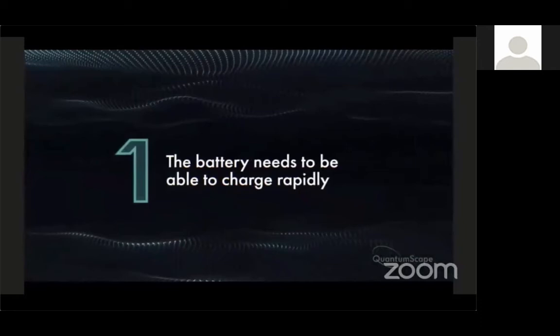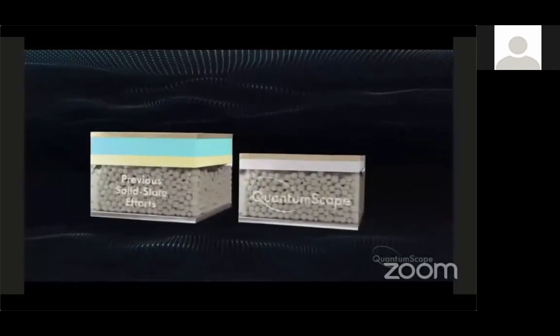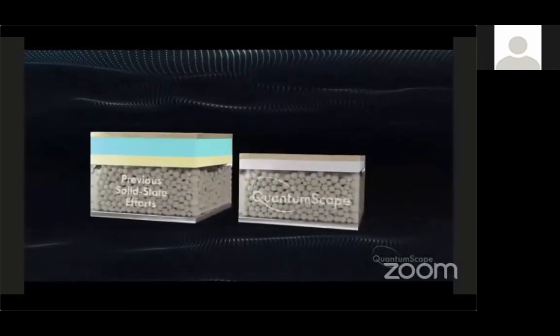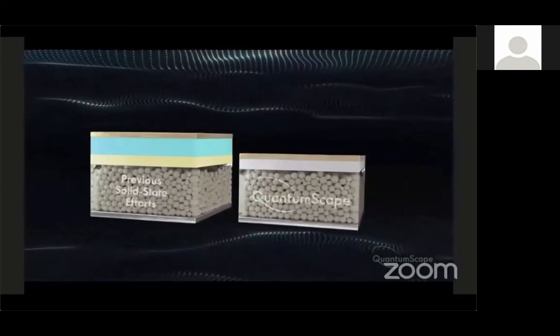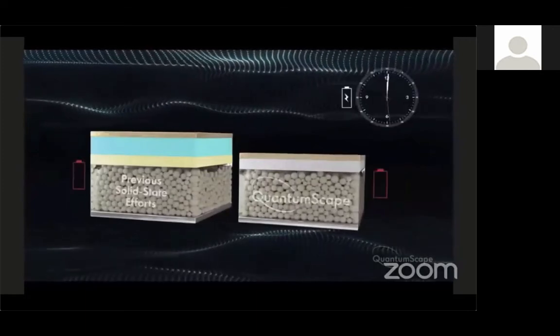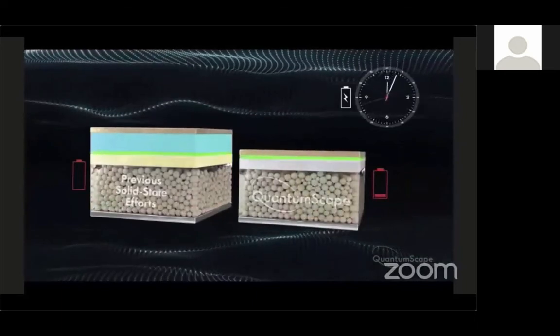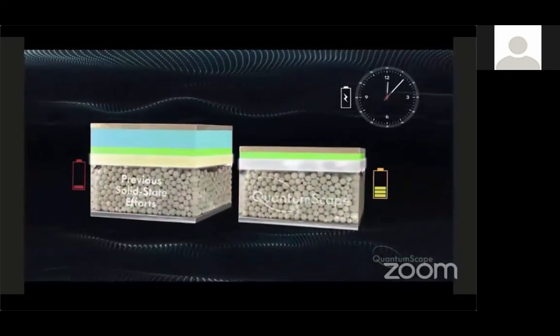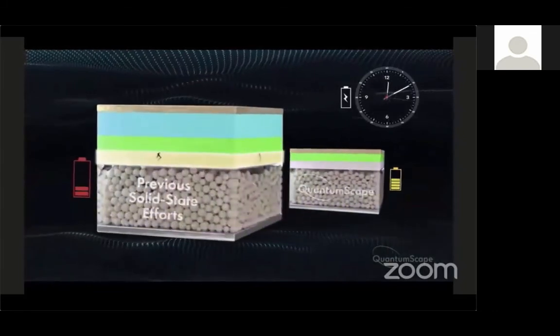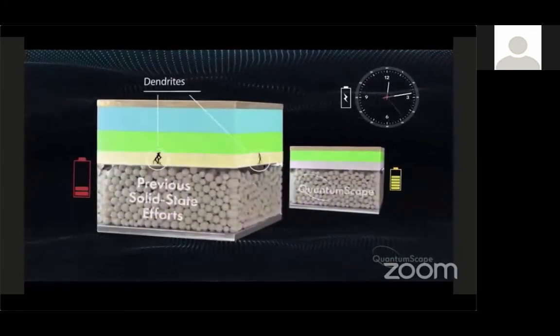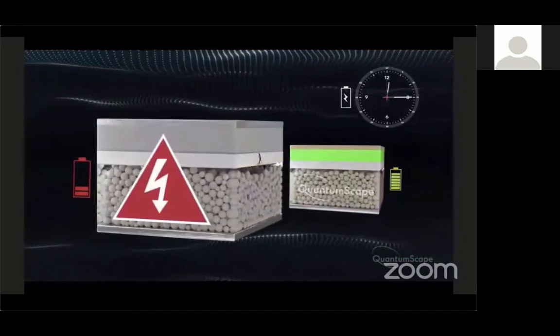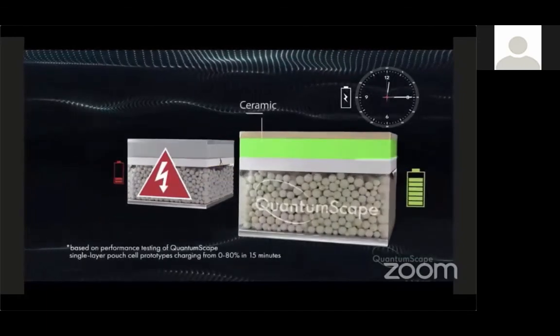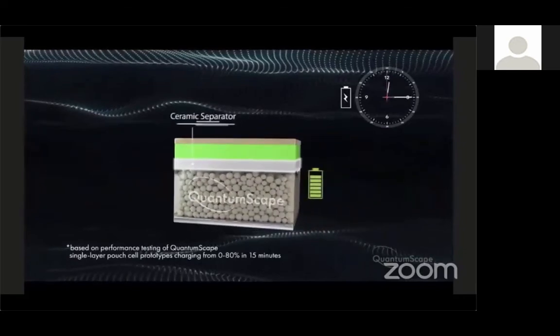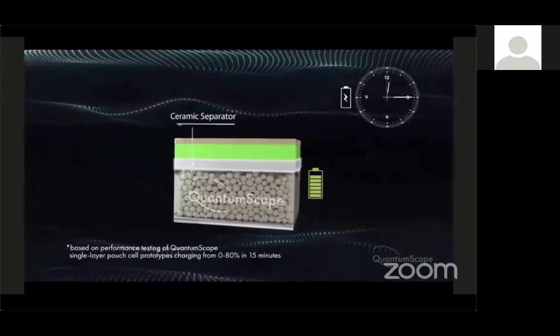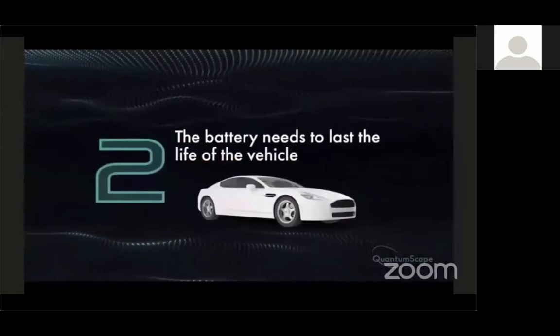1. The battery needs to be able to charge rapidly. Perhaps the most important challenge for a solid-state battery is the ability to withstand the rates of power that are required for fast charging. As the battery charges, the solid-state separator is stressed by the high current passing through. If the separator can't handle the current density, lithium metal dendrites will puncture through, short-circuiting the cell. QuantumScape batteries have a ceramic separator that has been shown to withstand the current density required for a 15-minute fast charge.